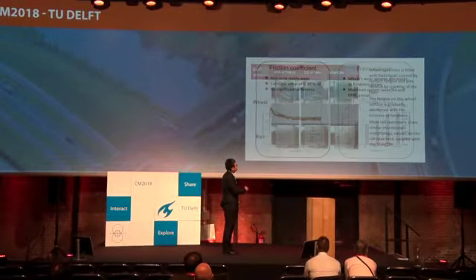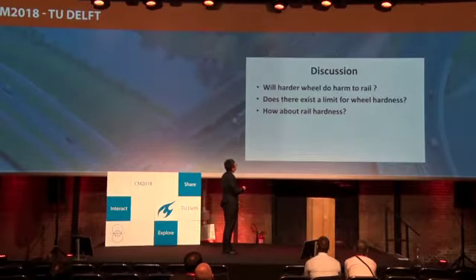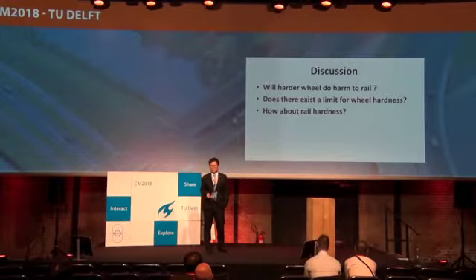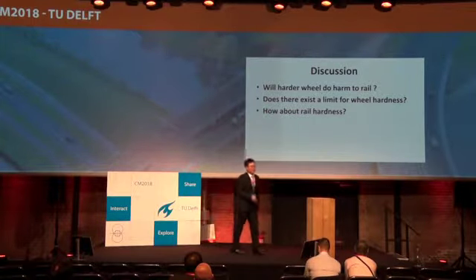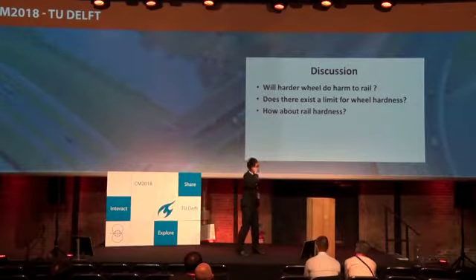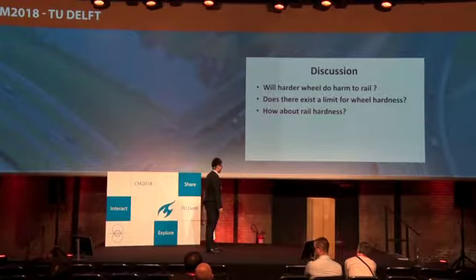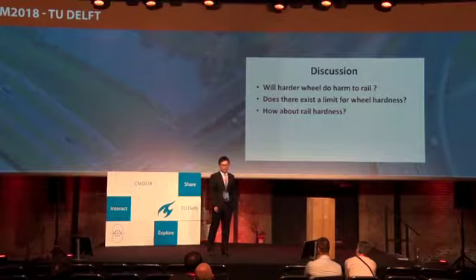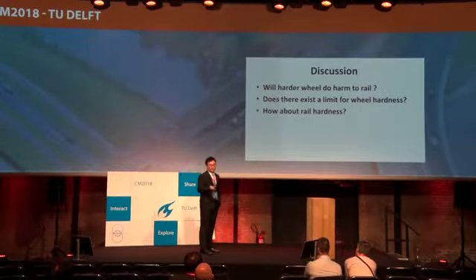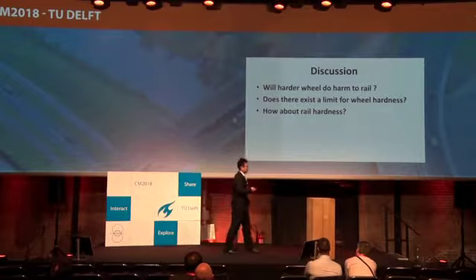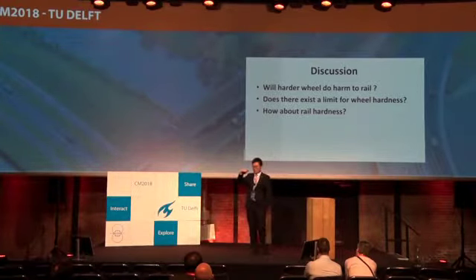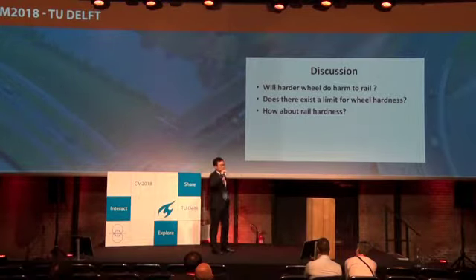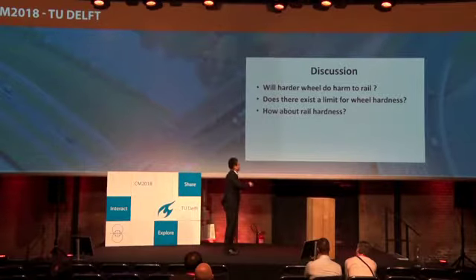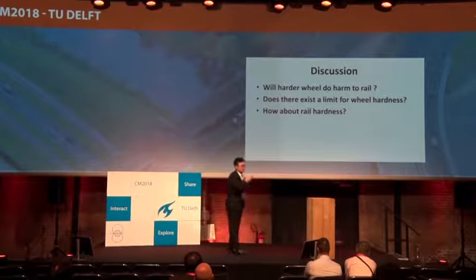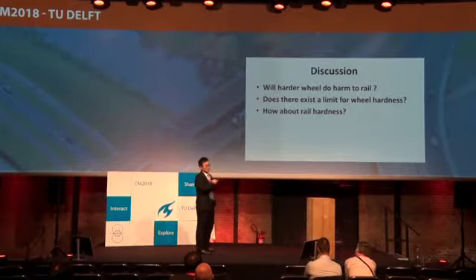So from this test, we see that a harder wheel might have some impact on the rail material and its wear volume, and maybe it degrades faster. But as we observed from the field tests in China, the wear volume of the rail in high-speed railway is so small that the vertical wear on top of the surface of the rail is less than 0.1 millimeter per year. So maybe there is plenty of space for improvement of the wheel's hardness.